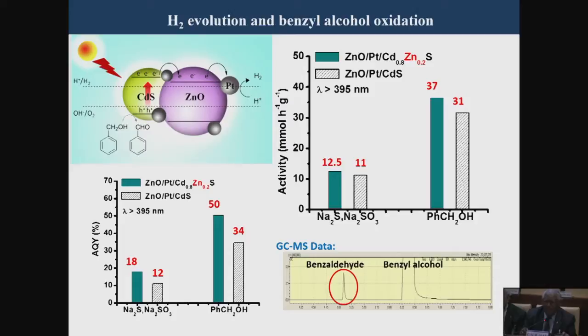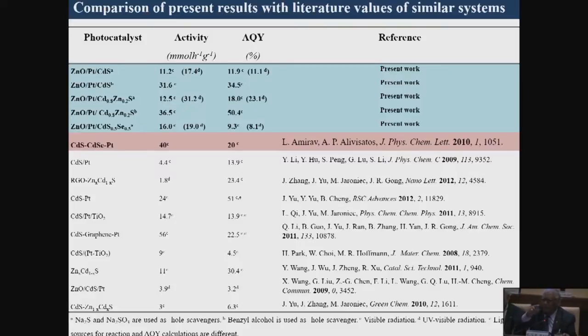When we did this work, what we got was a fantastic result. We have achieved quantum yields up to 50% and fairly high yields of hydrogen — 30 to 40 or 50 millimoles per hour per gram of catalyst. We showed that with very simple semiconductor heterostructures we can get very good yields of hydrogen with high quantum yields, somewhat comparable to what the Berkeley people did, except that our heterostructures are much simpler to make.